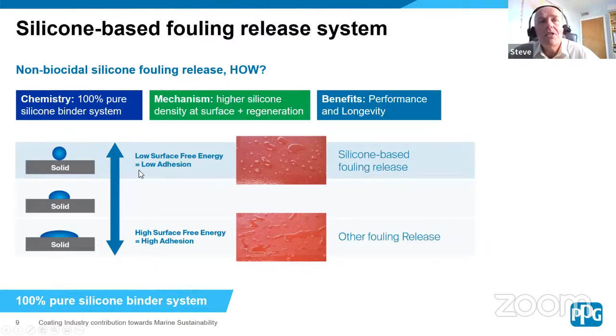And this is the basis of these biocide-free coatings. They work on the principle of low surface energy, low surface free energy, to be more precise. And that is a function of adhesion. It's much easier to adhere to a high surface energy surface. How does that scientific description translate into reality onto a coating? Well, here you can see a coating where water has been allowed onto the surface, and it's reminiscent of this schematic diagram. It's starting to wet the surface, it's opening out its contact angle. Whereas on a silicone release system, you can see the water beads very much in line with this schematic diagram here. It tries to minimize its contact point with the surface and substrate.